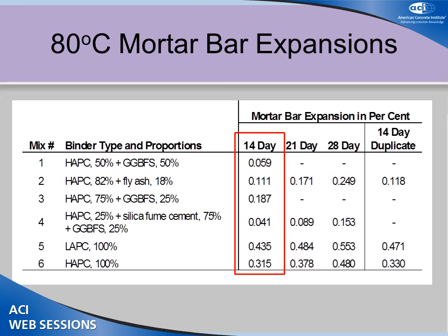And this gets to the heart of some of these comments or agencies that want to use a 28-day limit in this test, which I think is goofy. If you look at mix number 4 with the ternary blend, it would be 0.15 at 28 days, which would indicate it wouldn't pass. And as I'll show you, this mix has not reacted at all. We wouldn't expect it to react at all. When this test was adopted, you have to pick a test date with the test, and it's already accelerated. Using a longer test age, I think, is foolhardy.